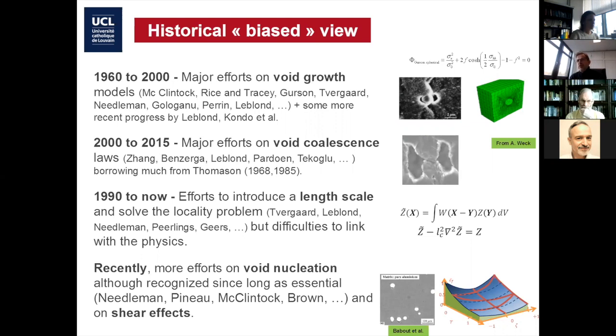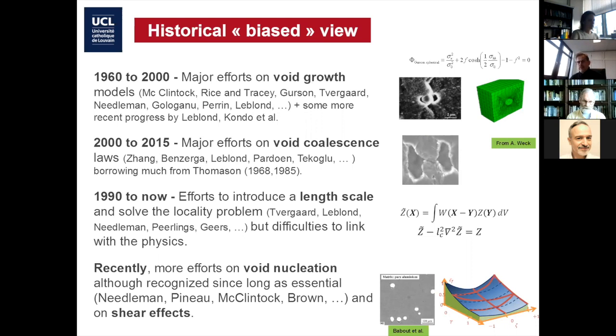When I'm reviewing this history, somehow you don't see very much the first step, which is void nucleation. Since the beginning, all the people working in that field know that at some point voids nucleate on second phase particles by fracture of the particle or decohesion. But there have not been so many studies to really try to formulate physics-based void nucleation models — they are essentially very simple models based on a critical stress or critical strain to nucleate voids. Another subject not sufficiently addressed except for the last 10 years is to take into account shear effects in the modeling of ductile fracture.